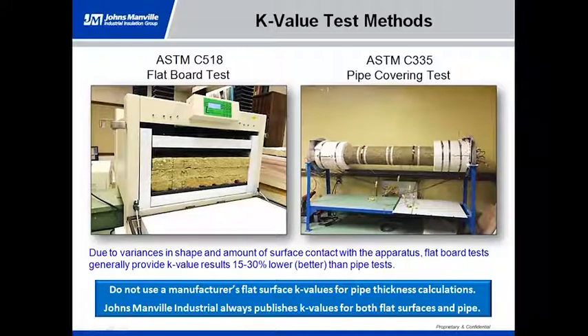So I just used the 75 degree mean temperature reference, and of course with industrial insulation it starts at 100 and goes all the way to 1200 to 1500 degrees. So the flat test is pretty straightforward. It's what they call one-dimensional heat flow, and those typically give the best results, or the lowest results, I should say. If you look at ASTM C335, it's a little bit different.